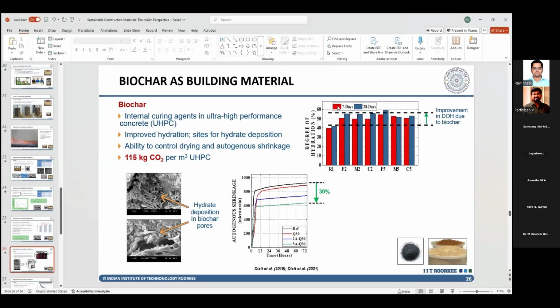But what we found was, yes, there was a very significant increase in the amount of hydration taking place. But a bigger find was that we were able to control the shrinkage in UHPC. Again, another problem in UHPC is that you trade the strength with shrinkage. Very high strength, but also very high shrinkage. So we were able to control that shrinkage by using biochar, because this biochar kept releasing water in different parts of the concrete, and it didn't allow the concrete to shrink as much as it would have without biochar.